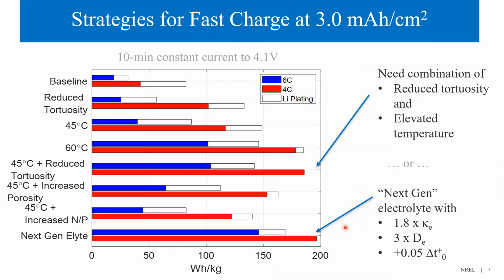To meet specific volumetric energy density and cost requirements, EV cells must have a sufficiently high loading of 1 to 5 milliamp hour per centimeter squared. The electrochemical model is used to investigate various approaches to enable extreme fast charging without lithium plating for cells with a loading of 3 and 4 milliamp hour per centimeter squared.